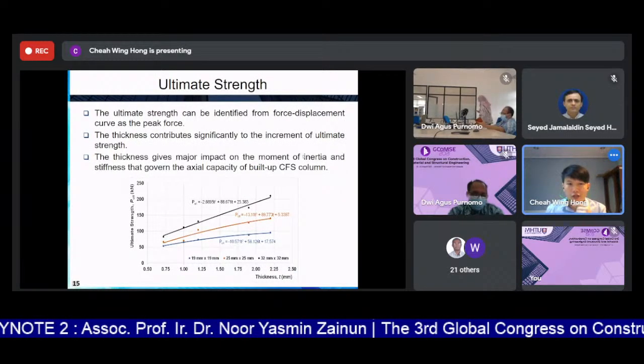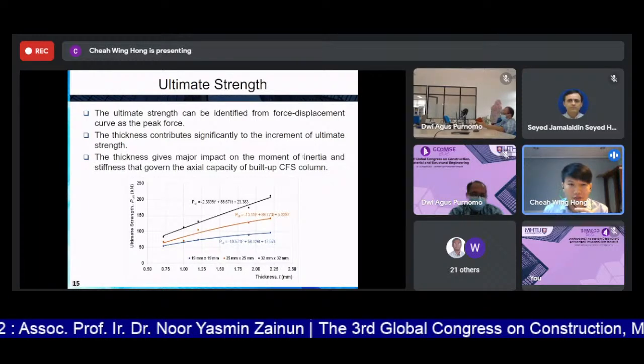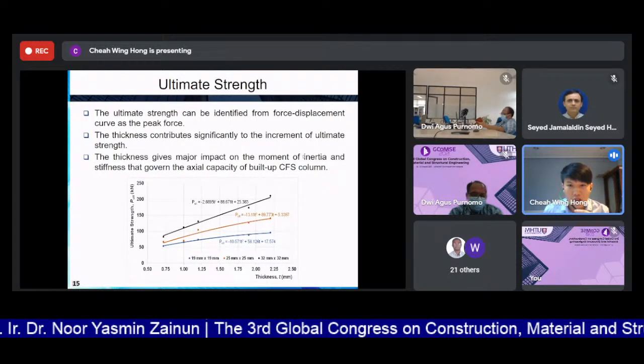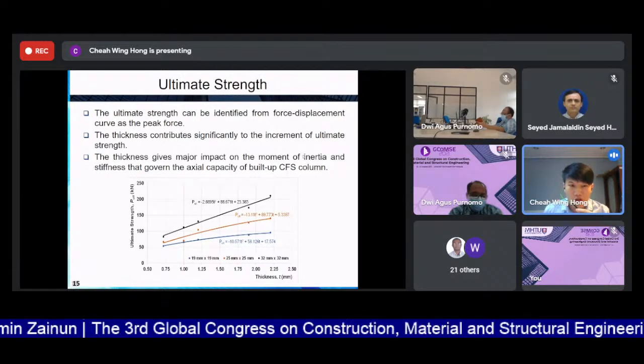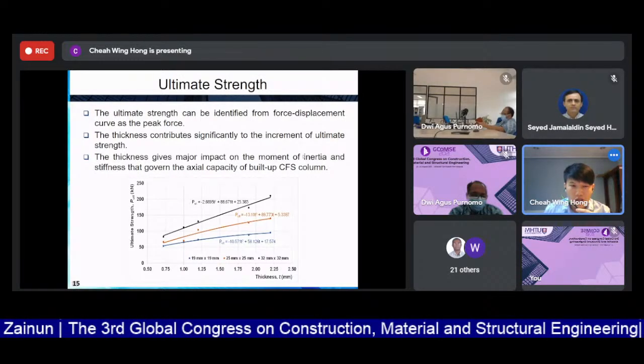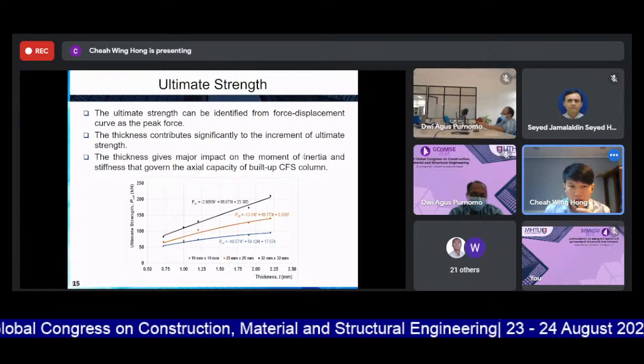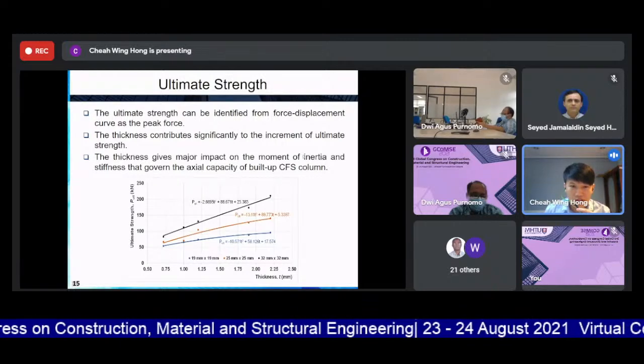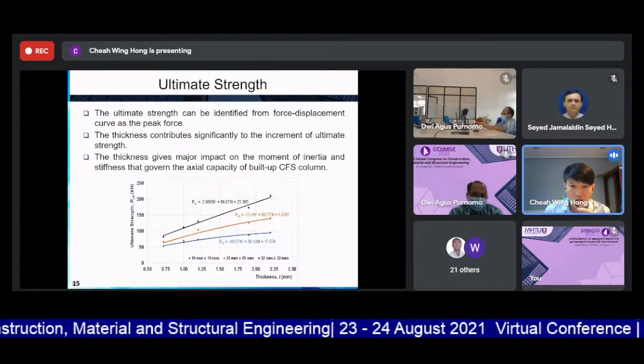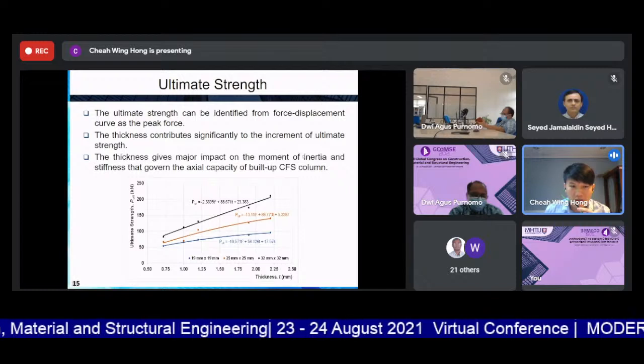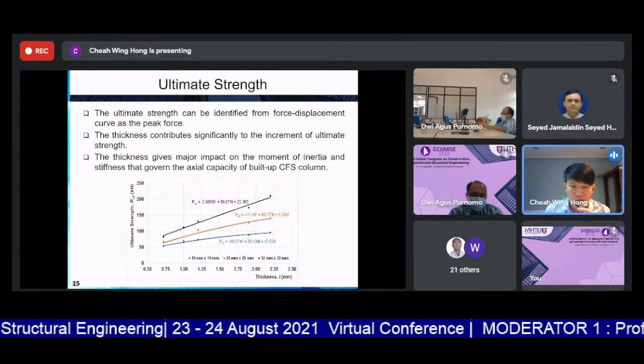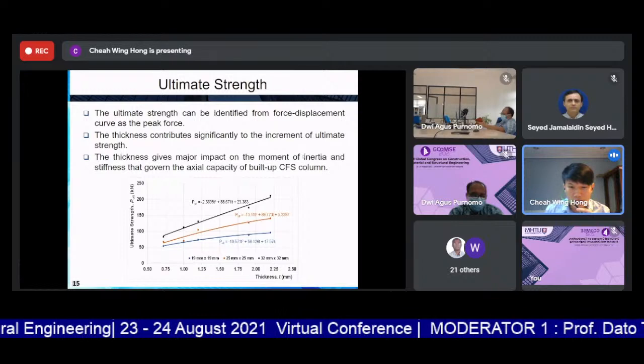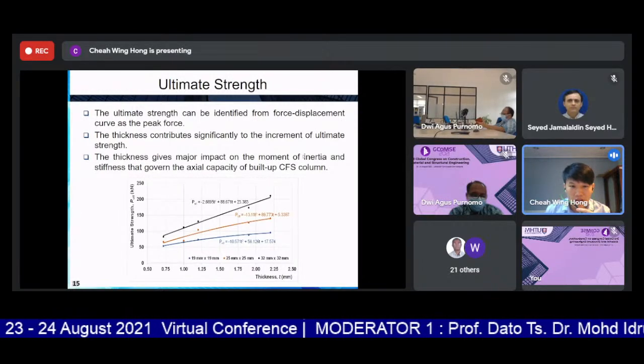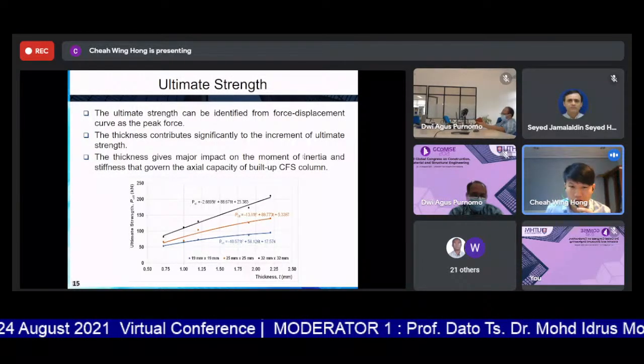For the effects of ultimate strength, it can be identified from the force displacement curve as the peak force. The thickness contributes significantly to the increment of the ultimate strength, and the thickness may give a major impact on the moment of inertia and stiffness that govern the axial capacity of the built-up CFS column. As we can see, when the thickness is increasing, the ultimate strength is also increasing for the three models.